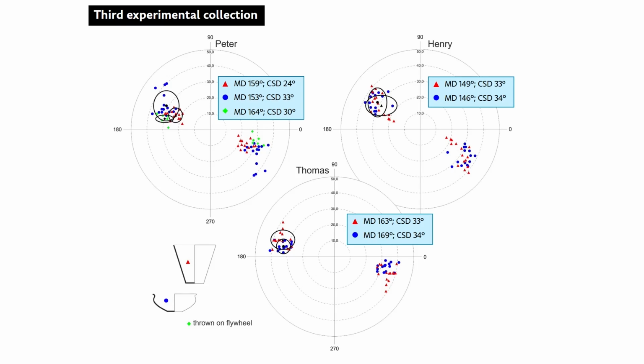But bowls exhibit similar orientation with a significant increase in circular standard deviation, with extremes exceeding 40 degrees. Throwing of pots on a flywheel shows a decrease of deviation from the horizontal axis, which is significant compared to conical pots thrown on the standard potter's wheel.